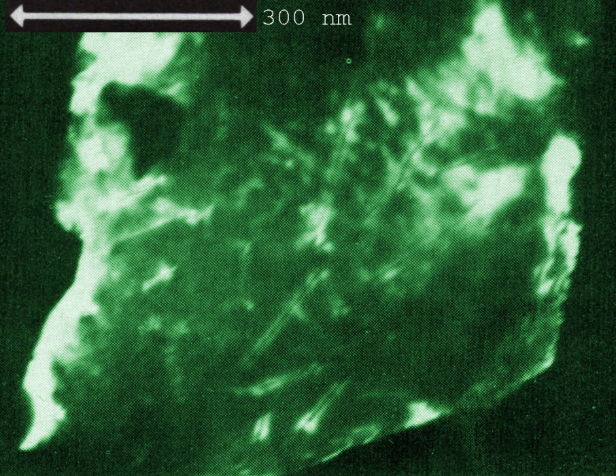Current rectifying pores, asymmetric pores are obtained by one-sided etching. The geometric asymmetry translates into a conduction asymmetry. The phenomenon is similar to an electrical valve. The pore has two characteristic conduction states, open and closed. Above a certain voltage the valve opens. Below a certain voltage the valve closes. Thermo-responsive channel, obtained by lining a channel with a thermo-responsive gel.